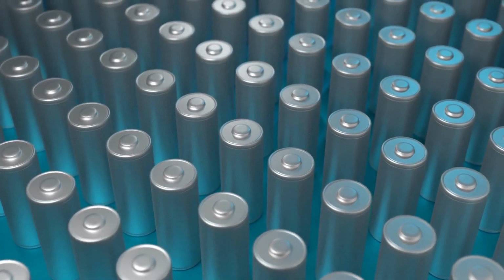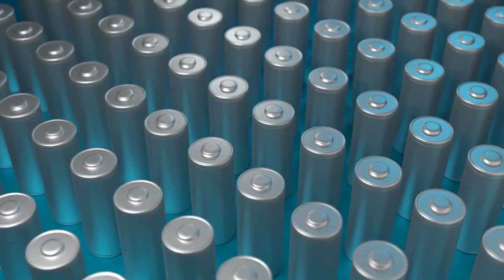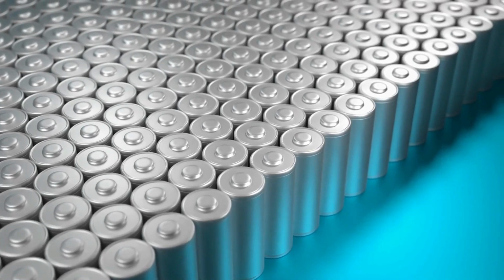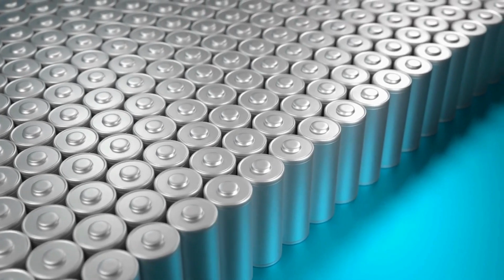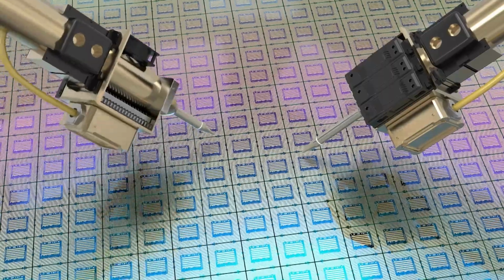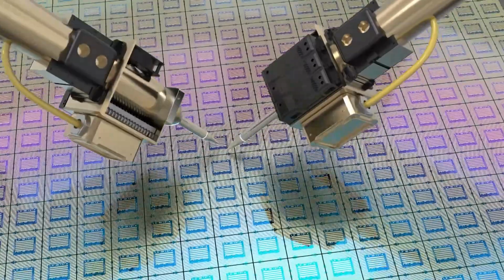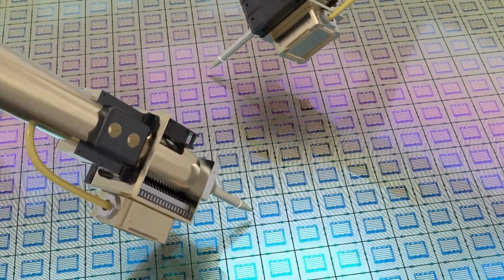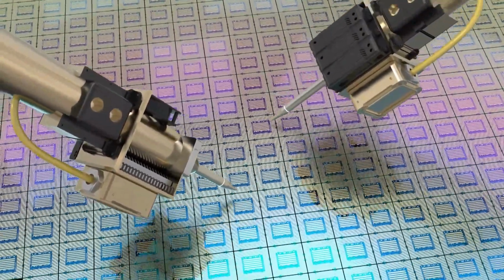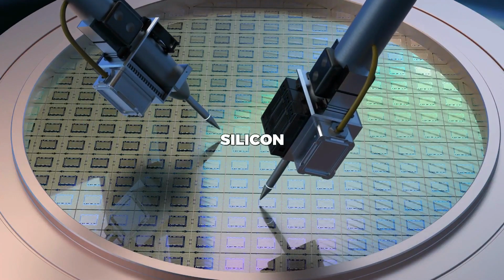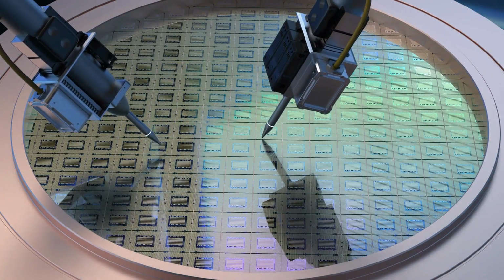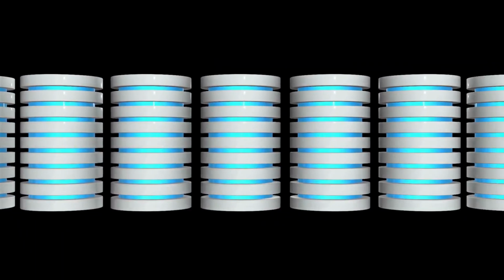Silicon can store about 10 times more lithium than graphite, but it tends to swell and crack, drastically reducing cell life. By forming the silicon into porous nanowires, arranged like a kind of forest, or longer wires with shorter wires in between, the silicon is able to tolerate swelling and resist cracking, extending cell life to the point that silicon anodes become a competitive technology.